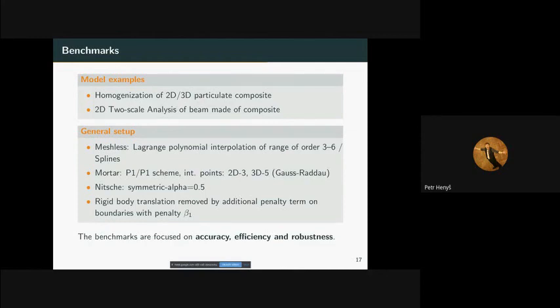Regarding the meshless, we use a Lagrange polynomial for interpolation of order 3 to 6, right? And in some cases, we also use, instead of Lagrange polynomials, splines, right? The splines are much more flexible, but the truth is that they are a bit more computationally intensive. Well, in the case of the mortar method, we needed to find suitable finite elements, the interpolation elements of the multipliers and the displacement field, and we found that the compatible space is Lagrange polynomials of the first order for both quantities of interest. We use a Gaussian integration scheme for 2D as well as for 3D, in one case with 3 integration points, and in 3D it was 5 integration points.